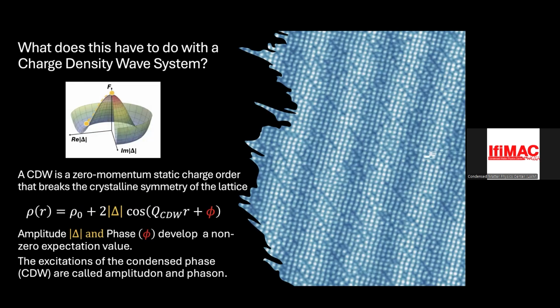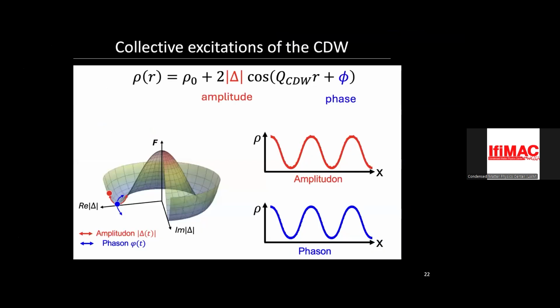So the question is, what does this have to do with the charge density wave system? And I think I've also already given you the answer. Basically, now let's consider this charge density wave. A charge density wave is a static charge order that breaks the crystalline symmetry of the lattice. And that means the charge density wave, just like the Higgs field below the CDW transition, has an amplitude and a phase, right? And it also breaks the symmetry of the crystal. So these acquire non-zero expectation values. There are two kinds of excitations of a CDW. One is called a phason, and the other is called an amplitudon. And it's these excitations that I'm going to talk about today.